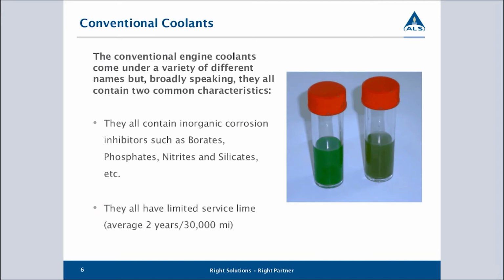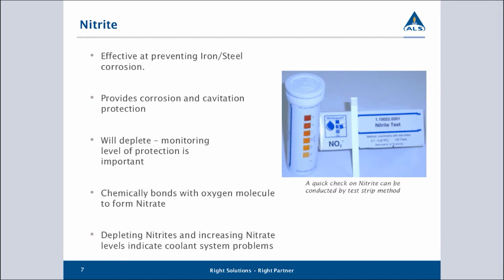Conventional coolants have a wide range of additives that can be present in them, and normally there'll be more than one. Sodium nitrite is probably the most common inhibitor we're seeing in use in conventional coolants. These are very effective at preventing corrosion on iron. But sodium nitrite doesn't work very well with aluminium systems. So if you have aluminium, you tend to find silicates are more common in the conventional coolant space. Sodium nitrite, as I said, is the most common, and monitoring nitrite depletion in a coolant is a very essential part of monitoring the life of these coolants and making sure that they still work effectively.